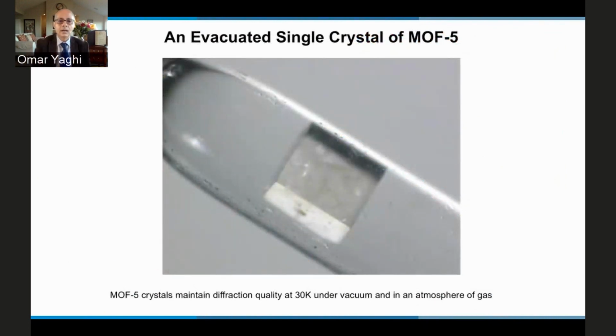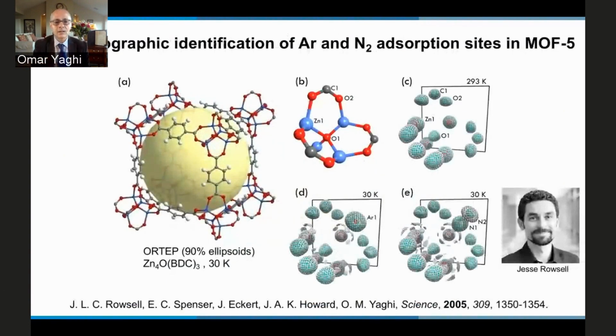So to really show where this high surface area is coming from, we took a crystal of MOF5, you see it here, and put it in a capillary and cooled it down to 30 Kelvin. Most materials, especially porous materials, will lose their monocrystallinity when you cool them down to 30 Kelvin, not MOF5. Even though the crystal was completely evacuated and cooled down to 30 Kelvin, it maintained its monocrystallinity. And this allowed us to take, for the first time, a single crystal structure using X-ray diffraction of the framework without anything in the pores.